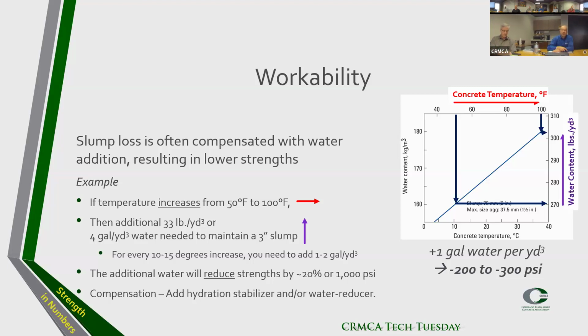That's just a recommendation for the ready mix producers that they actually add any water addition to their tickets. Sometimes it's actually automatically done by their batch system, just to make sure that we have all the facts should we have an issue later on. Again, slump loss is just because of the temperature difference. It's quite a bit, so we have to be careful that we don't add water, or at least not too much water at the construction site. We dilute the concrete and we reduce the strength.